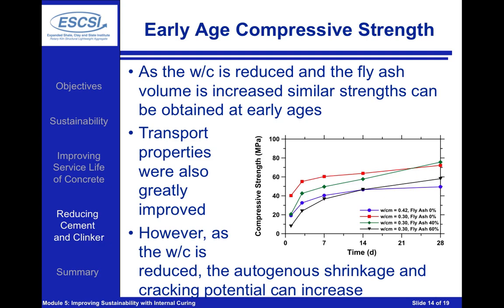However, this is where we may be able to take advantage of those improvements in strength in a way that we can actually make our concrete mixtures more sustainable. Here what we're going to do is use a lower water to cement ratio. However, we're going to replace a large portion of the cement with a supplementary material like fly ash in this particular case. So replacing 40% of the cement resulted in the green line that you can see, and replacing 60% of the cement resulted in the black line that we see on these mixtures. So one of the big takeaways is that if we replace some of the cement with fly ash and we alter our water to cement ratio at the same time, we can still get very similar early age strengths in these systems, which would be very important when it comes to early strength for formwork, early strength for using that structure at early ages.